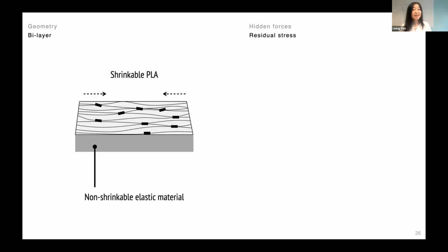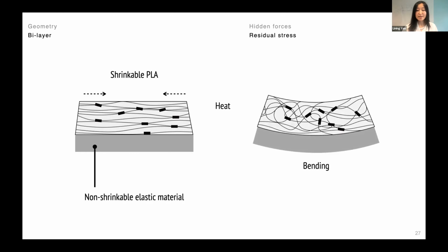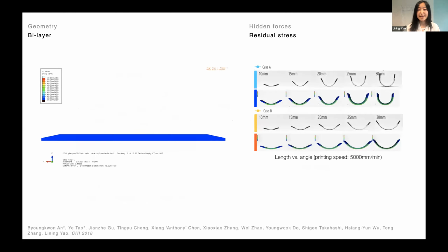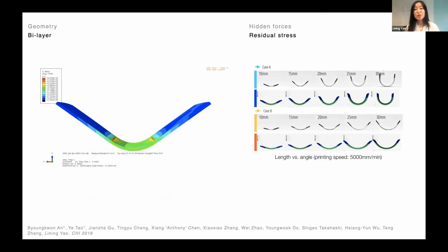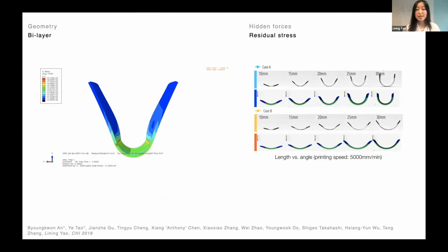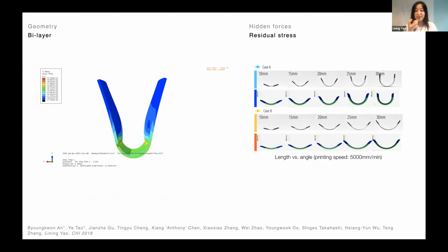So firstly, if you want to play with the geometrical concept of a bilayer, what you can do is print the shrinkable components on a non-shrinkable substrate. And suddenly you are designing a bilayer structure that can bend, but in a controllable way. One way to control the bending curvature is to control the length of the actuator. It's so straightforward, almost too simple to explain to this community. But anyway, the point being you can control the bending curvature of each hinge area.